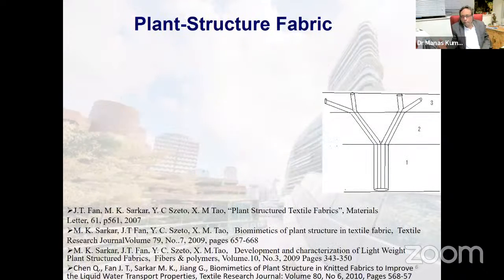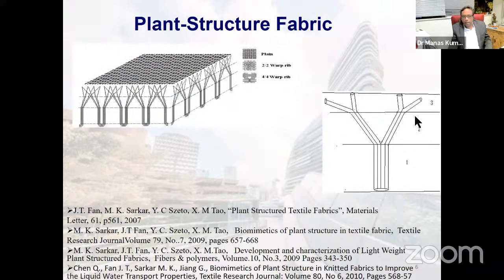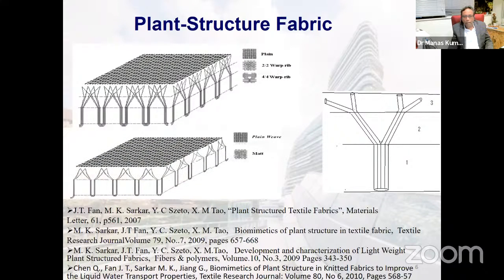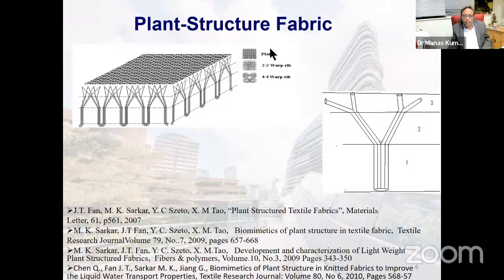So this is a natural plant structure. The main stem is divided into branches, which are again divided into sub-branches. Imitating that, we developed a three-layered plant structure fabric where in the bottom layer we use a 4x4 warp-rib design, in the second layer we put a 2x2 warp-rib design, and in the upper layer we put the plain design. So water can be absorbed by this and transported this way, moving faster to the outer layer. So that's our natural kind of branching structure.